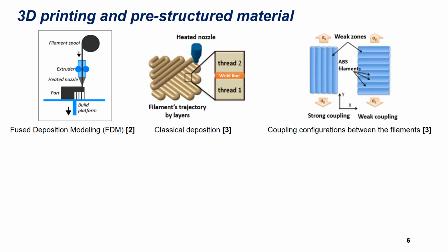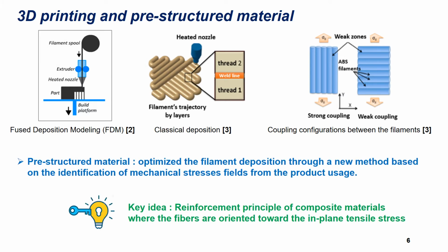Thread deposition can be not suitable to the mechanical constraints of a product, according to its use, especially when a weak coupling occurs between the filaments. Therefore, the filament deposition must be optimized through a new method based on the identification of mechanical stress fields from the product used. The key idea is to orient filaments toward tensile stress, allowing a strong coupling between the filaments, similar to the principle of reinforcements of composite materials.